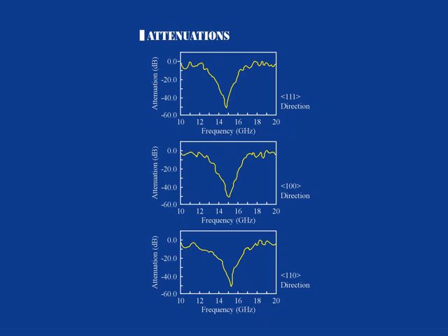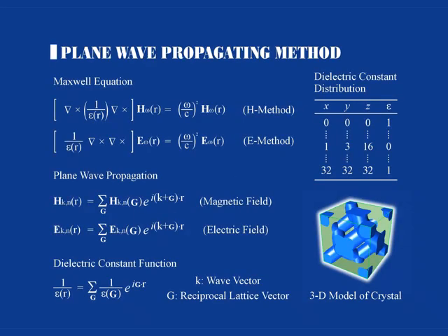Okay, so next, the electromagnetic property of the photonic crystals is possible to calculate by solving the Maxwell equations. In this case, a plane wave propagates into the photonic crystals in all crystal directions. The most important, most difficult thing is how to enter the 3-dimensional structure into the Maxwell equations. However, in this case, the computer graphic data were cut into 32 by 32 by 32 XYZ data, and the digital data were entered into the Maxwell equation automatically.